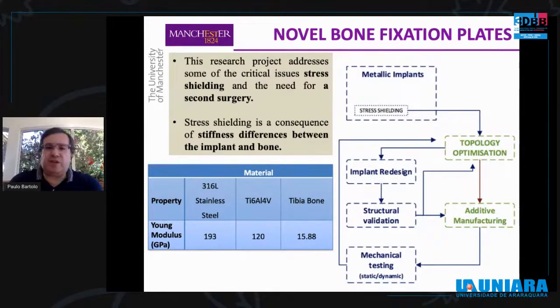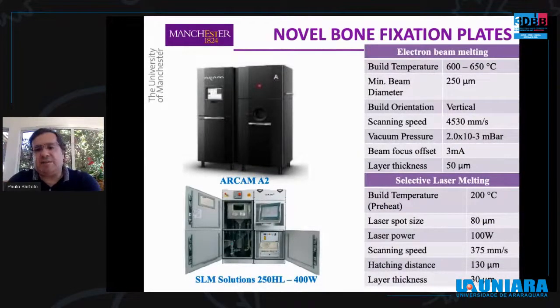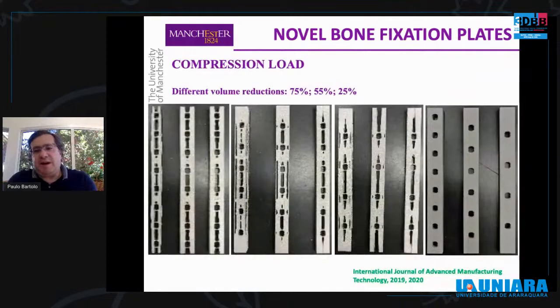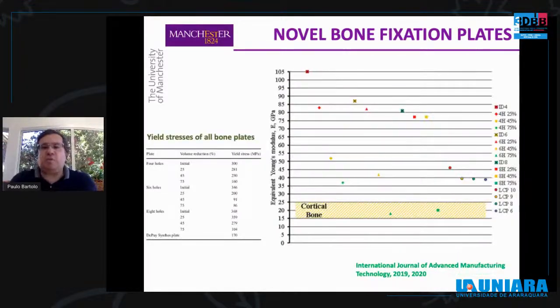We run topology optimization considering different loads and volume reductions, and as I mentioned, we use two different technologies, powder bed fusion technologies, but using different principles to print the plates. One was electron beam melting, and the other one was selective laser melting. The plates were, as I mentioned, optimized considering different loading conditions and different volume reductions. And by the end, it was possible to obtain a couple of new designs with properties in the cortical bone region. So we were very happy with these results.